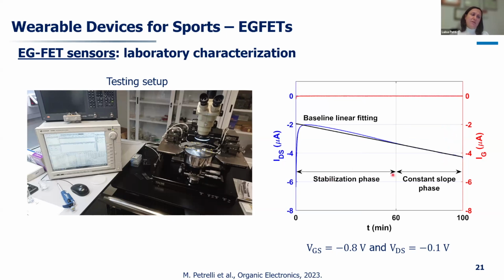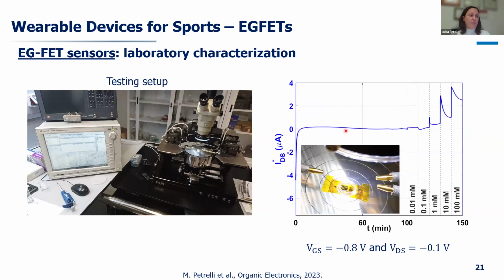So what you see, this is the stabilization phase. Then we have a constant slope phase. Stabilization is typically an hour. And if we do a baseline fitting, we can really then measure only the variation in the current, the increases in the current in this case, for the different concentrations.